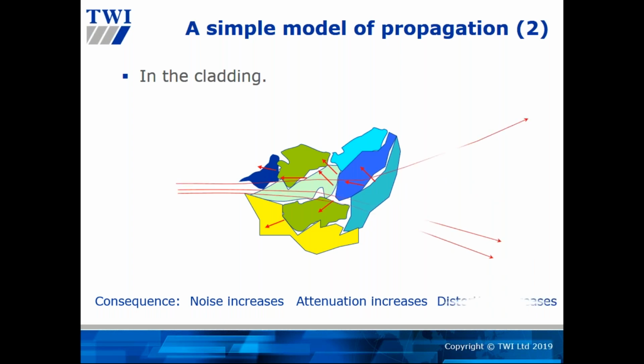And then thirdly, the anisotropy of these grains, the fact that the wave has to travel through different elastic mediums across the boundaries, essentially means that the energy vector changes, which means that the sound beam is distorted. And all of these effects can be seen in both cladding but also in austenitic welds. And there are a lot of thick section austenitic welds, which you will find in the primary circuit of PWR plants, and certainly in SMRs.